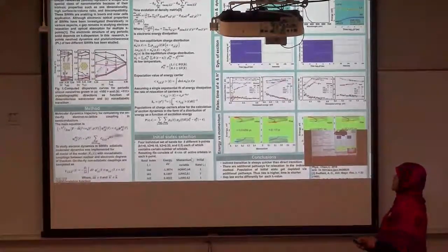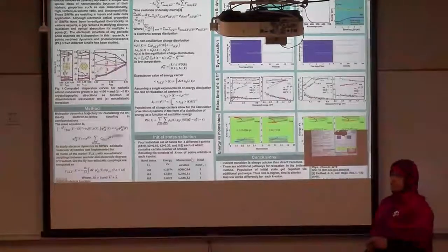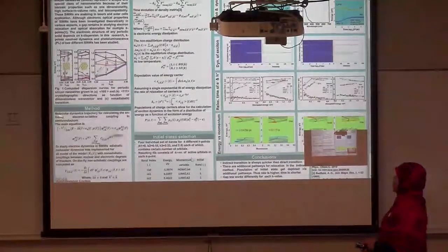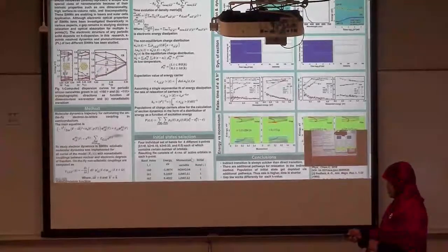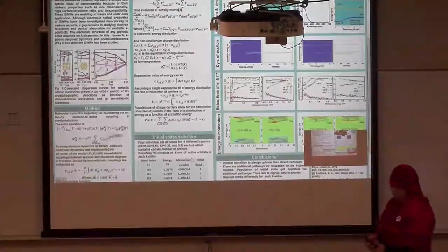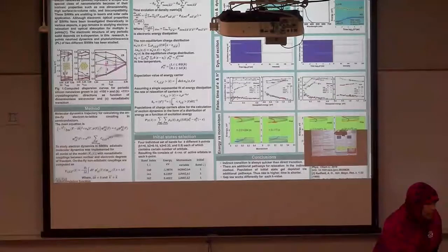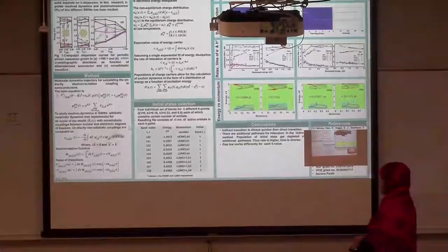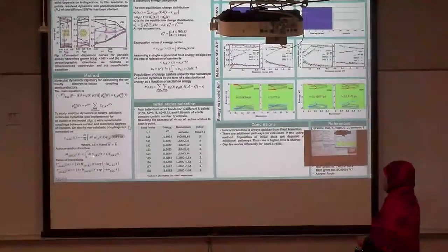When they are coming back, they can couple with the nuclear motion. Using this equation, we can calculate the coupling between electron and nuclear motion. That is called non-adiabatic coupling. Once we have this non-adiabatic coupling, we can derive the autocorrelation function here, and using this autocorrelation function, the rates of transitions can be calculated.